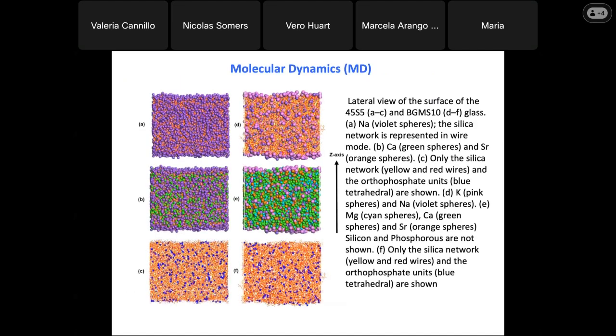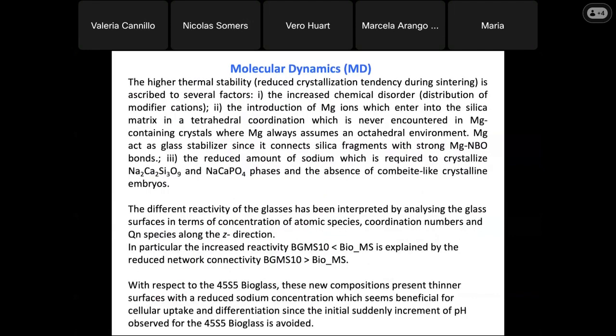So before proceeding with in vivo implants, we performed a molecular dynamics study, which is very useful for glasses because it permits to analyze the behavior of the glasses based on the composition. And it was demonstrated that the higher thermal stability of these novel bioactive glasses could be ascribed to several different factors, such as the increased chemical disorder of the network, the introduction of magnesium in the silica matrix, and the reduced amount of sodium which is required to crystallize some crystalline phases.